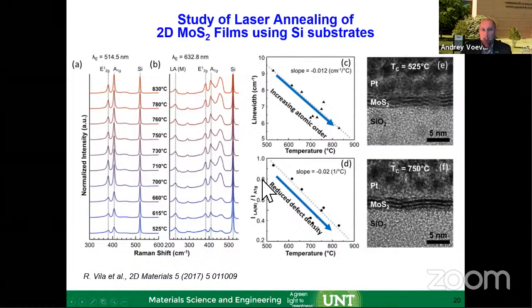And as a result of this very interesting work, again, you can see the citations in here. I advise you to follow up on that. This is work by Dr. Glavin and his team. It is possible to see reduced defect density and increasing atomic order as you're heating up locally. Now the local heat is only held for a few seconds, so there is a challenge to deposit with less substrate damage if you're using a polymer substrate and not silicon oxide.